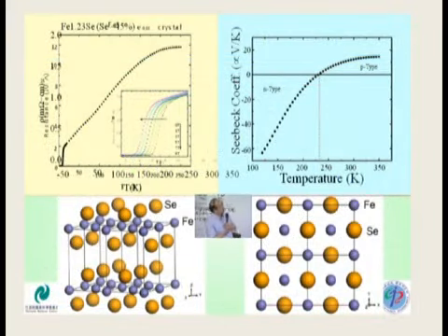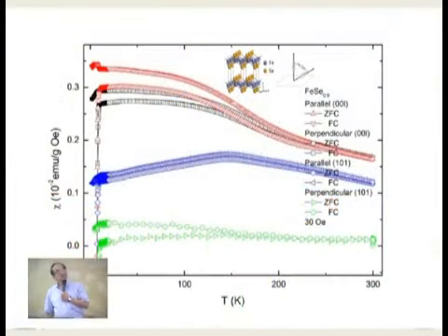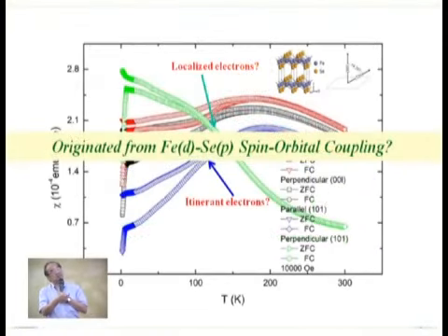But why do we have this distortion? Well, we further look into this high temperature part again. As I mentioned, there's a crossover from the band crossing, right? And this is the Seebeck coefficient at the high temperature. So we start to look at whether there's some other feature. A simple way is to study the magnetic property. Without going through detail, we can look at the crystal in different orientations. This is the crystal, and you can measure the magnetic property along this or perpendicular, and you see a very strong anisotropy between the two orientations.